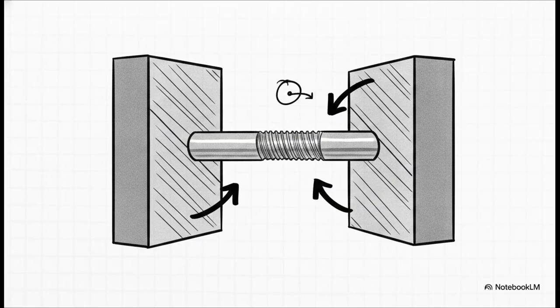We don't cut the threads, we roll them. The shank of the bolt is basically squeezed between incredibly hard dies that press the thread pattern right into the metal. And this is so crucial for engineering efficiency. Squeezing the material induces severe compressive residual stresses at the roots of the threads. Since microscopic cracks need tensile stress, or pulling apart, to grow, these compressive stresses actively fight off fatigue cracks. Plus, because we aren't shaving away any metal, we literally save 15 to 20% of the raw material by weight. That is massive at scale.